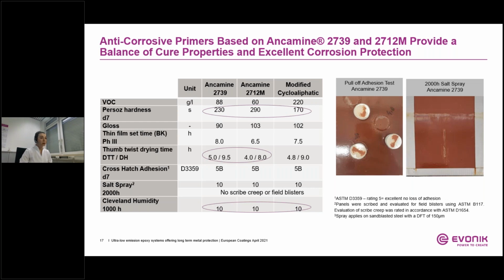Ancamine 2739 and 2712M provide fast dry as measured by the thumb twist method, corresponding to 9 hours for Ancamine 2739 and 8 hours for Ancamine 2712M, which is comparable to the modified cycloaliphatic amines.